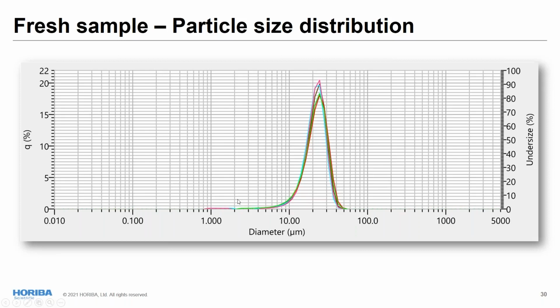So here we see a triplicate of measurement and samples, which means we have 9 results here. So you can see the repeatability of this analysis is very, very good. One of the main results we have is the median size of your particles, which is also called the D50. In this case, for the fresh sample, it was 22.4 microns.